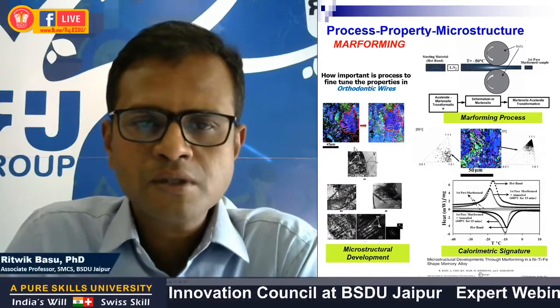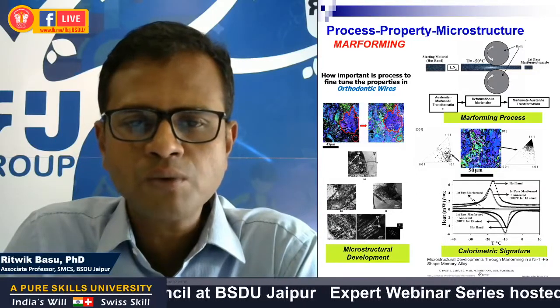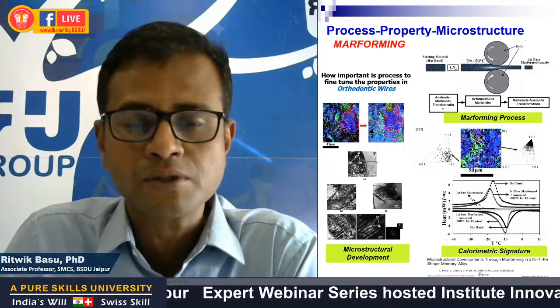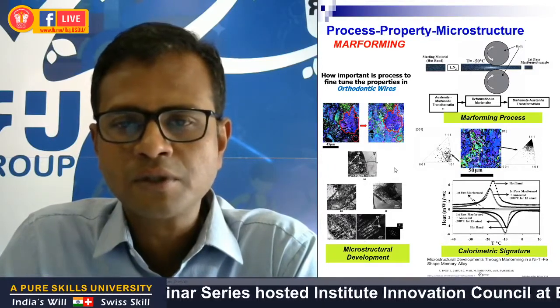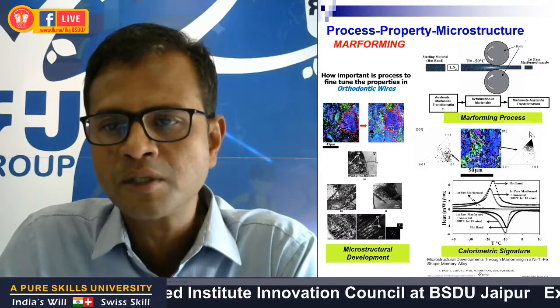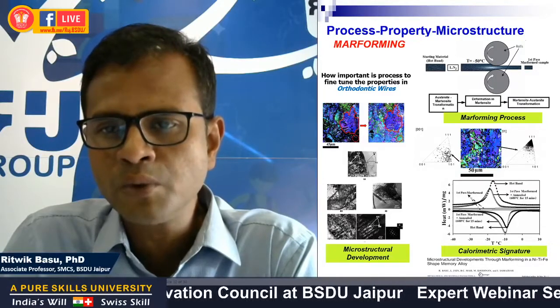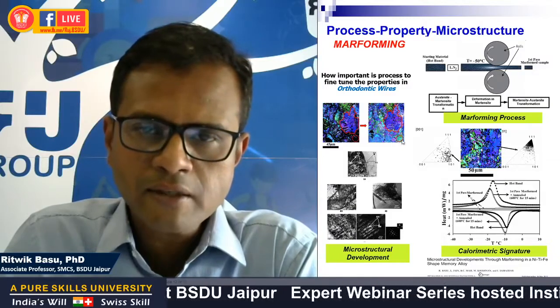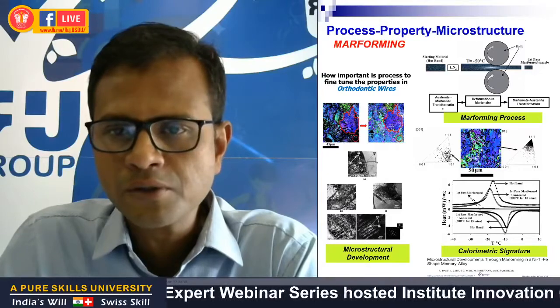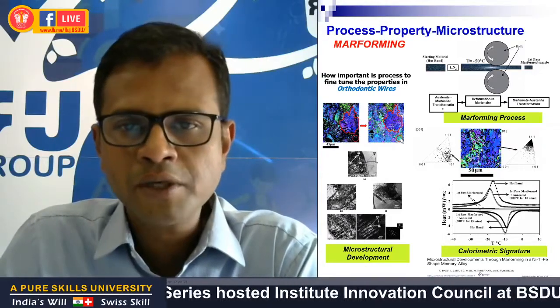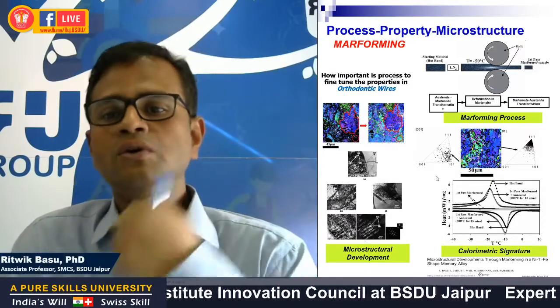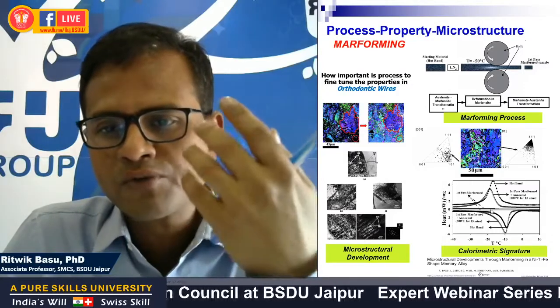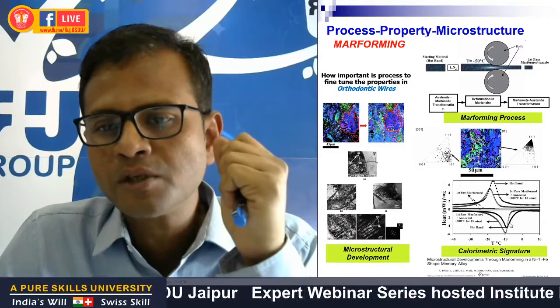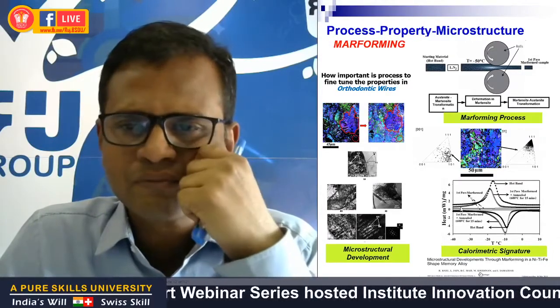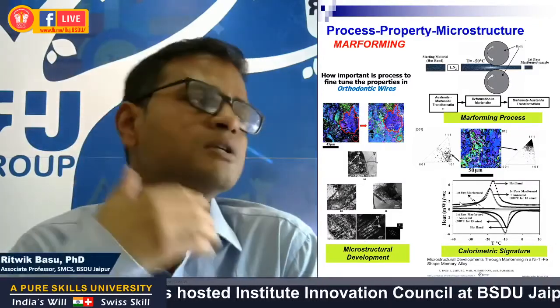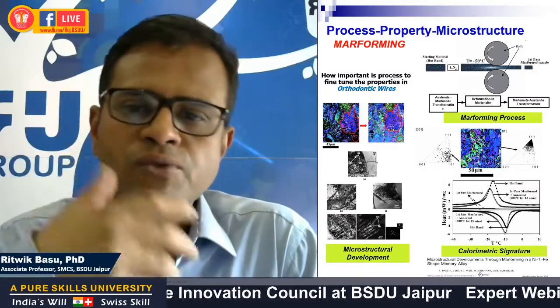So we tried to further look into these dislocation structures through transmission electron microscopy, and we found that certain grains had these banded structures of dislocations. So these grains which had these dislocation structures were found to have orientations typically denoted by ND parallel to 111 orientation, so these blue colored grains. And interestingly, upon annealing, fine clustered grains of ND parallel to 110 orientation, these green grains, were seen to be evolving in these regions of higher dislocation density. So marforming without annealing shows no phase transformation. However, slight annealing could bring back the transformation, seen through this pair of peaks in the calorimetric plot. So the transformation here I'm referring to is the transformation from the high temperature state to the low temperature and the reversal of phase transformation.